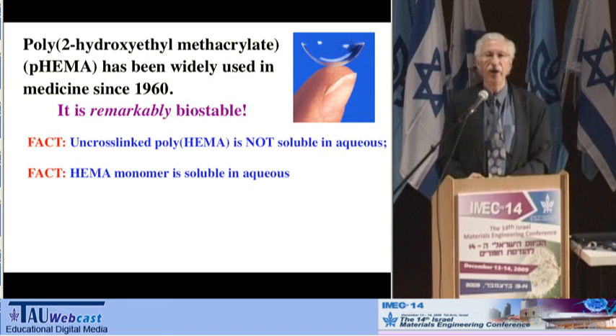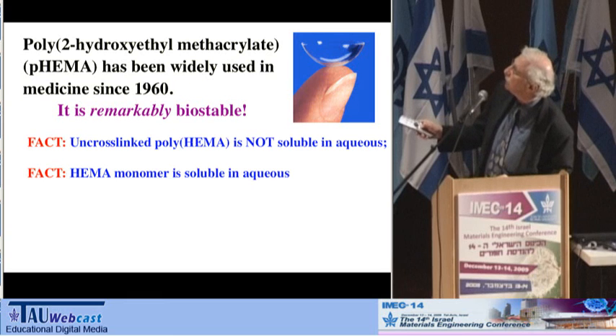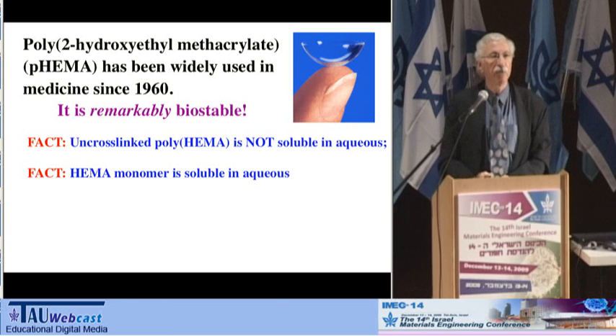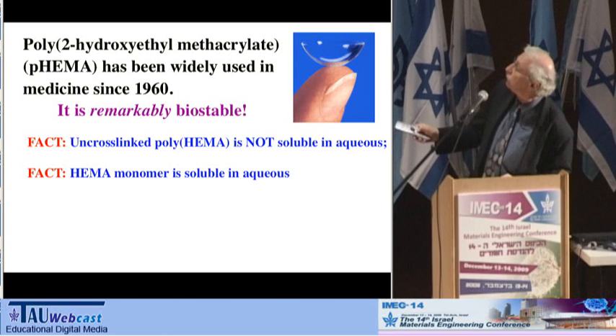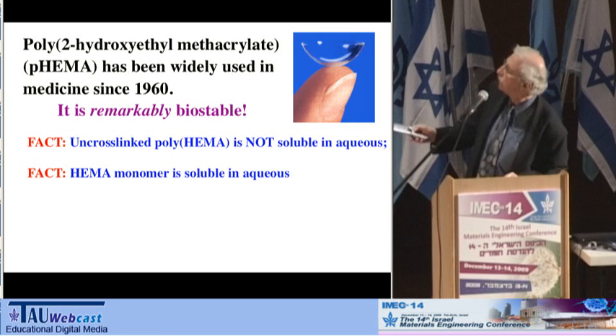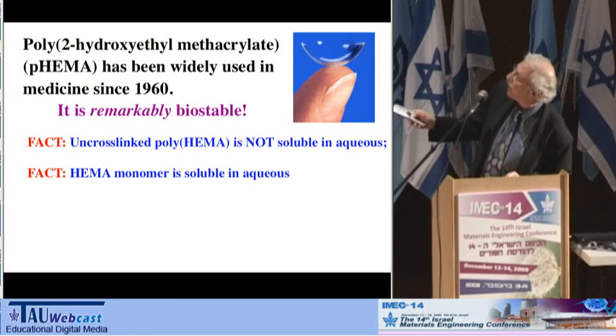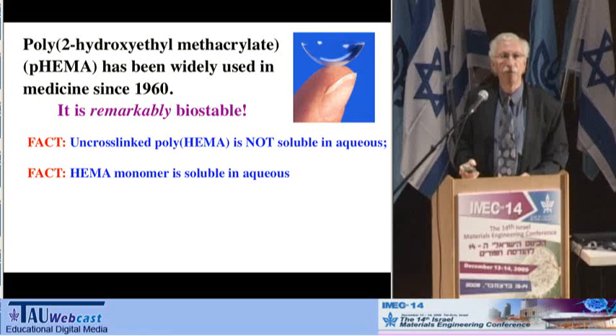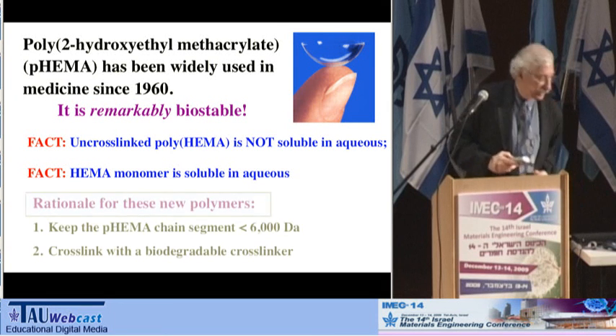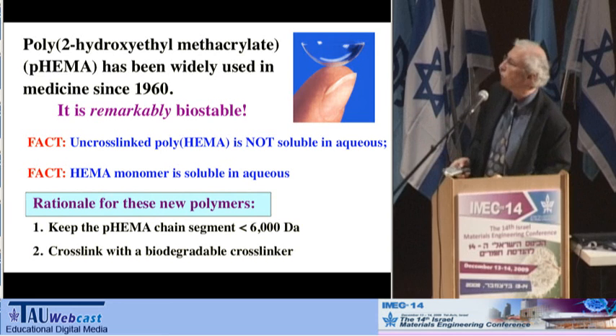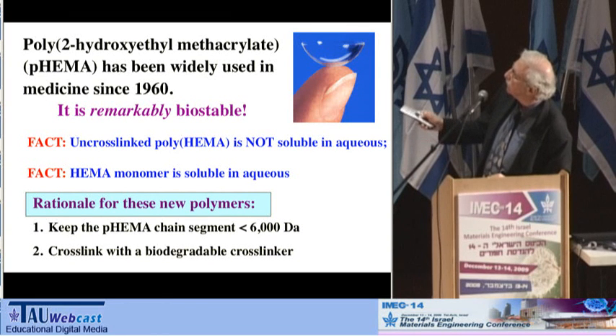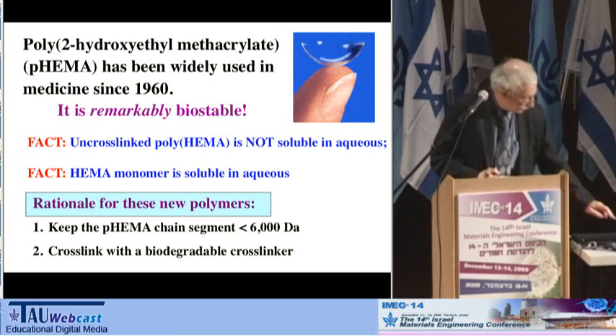But there are two facts that we do know about this. One is that if we take this material in an uncross-linked form, it's simply not soluble in aqueous solution. Another fact is that the HEMA monomer itself, the low molecular unit, is soluble in aqueous solution. That makes us think that somewhere between the monomer and the polymer, there might be some degree of polymerization that is soluble. And in fact, that is the case. So the rationale for these new polymers is to keep the HEMA chains less than 6,000 Daltons and then cross-link them with a biodegradable crosslinker.